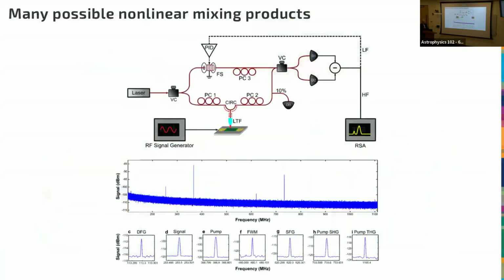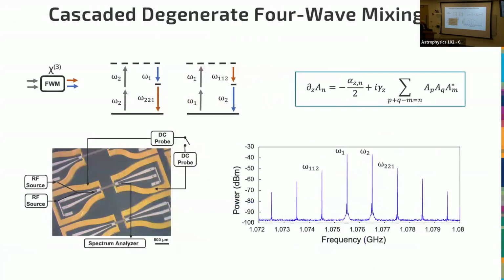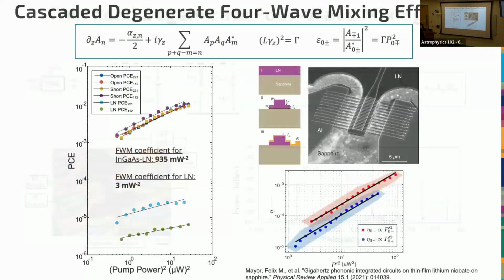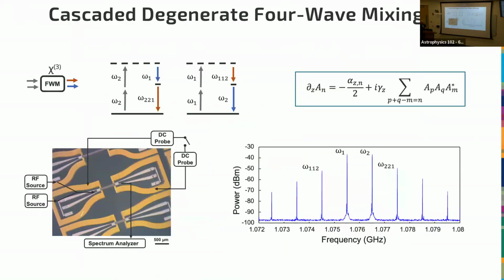And I'll say more about that in a second, but I'm going to go a little bit faster here. Let me just say that we can also measure degenerate four-wave mixing, which is essentially the Kerr nonlinearity. Now, Professor Safavi-Naeini has this great paper where they measured four-wave mixing for acoustic waves in a waveguide in lithium niobate on sapphire. They launched acoustic waves in this lithium niobate waveguide, and basically what they did is they put two pump tones in. So they have a pump at omega 1 and a pump at omega 2, and they generate this Kerr comb.